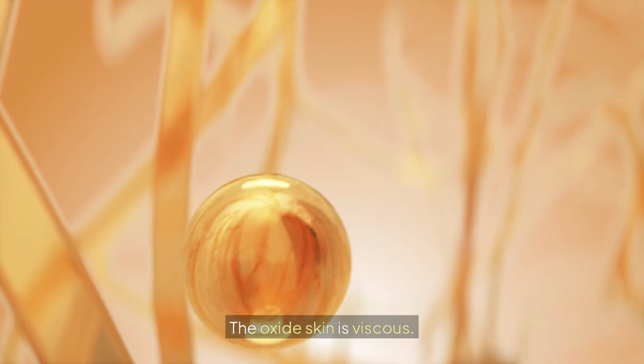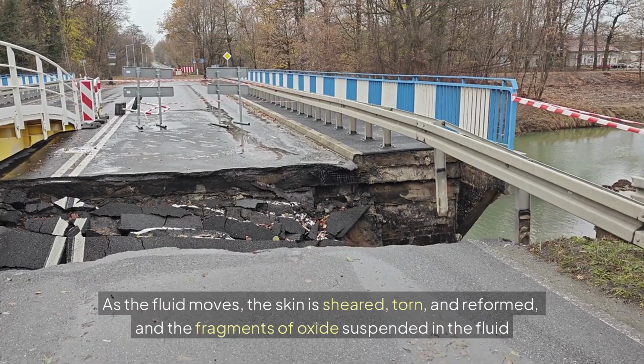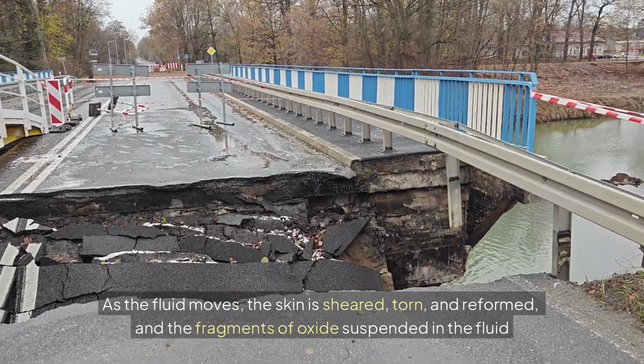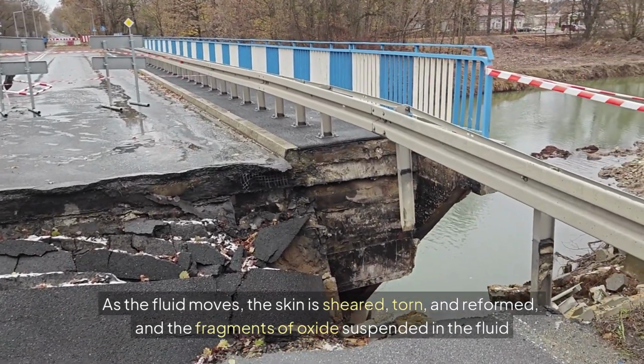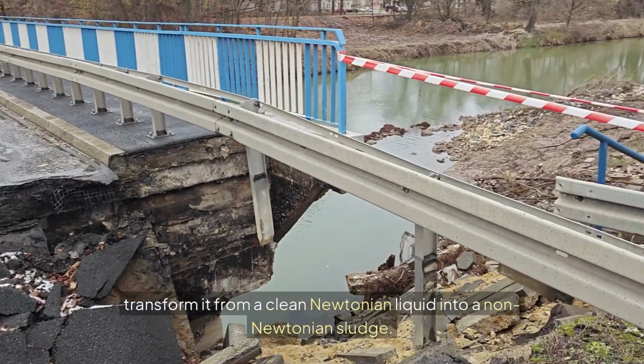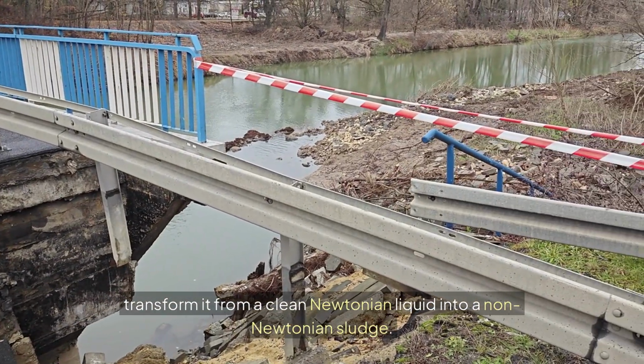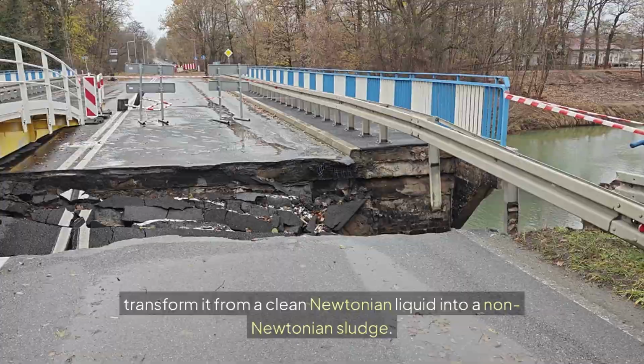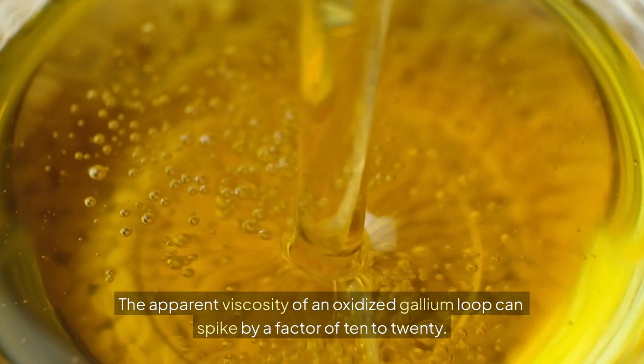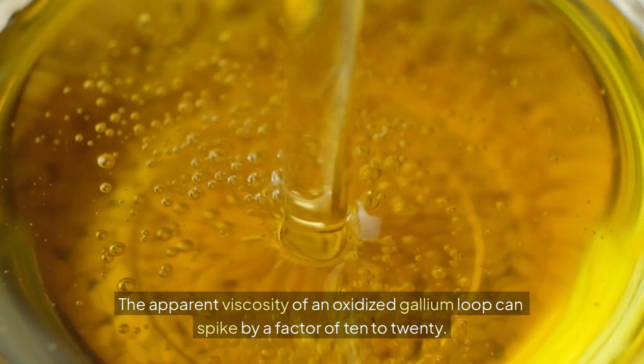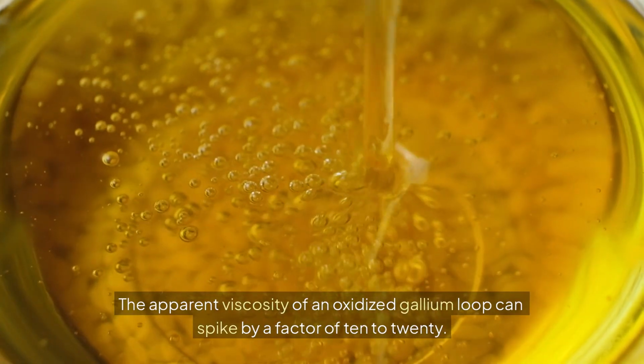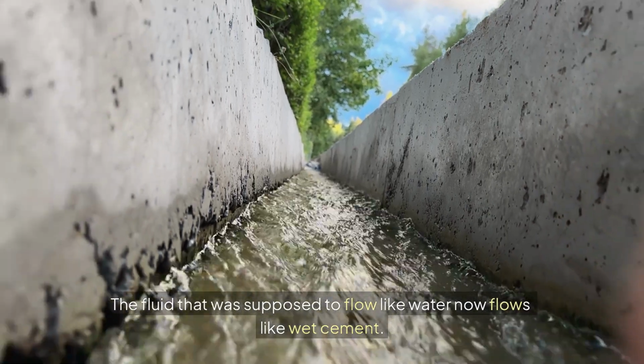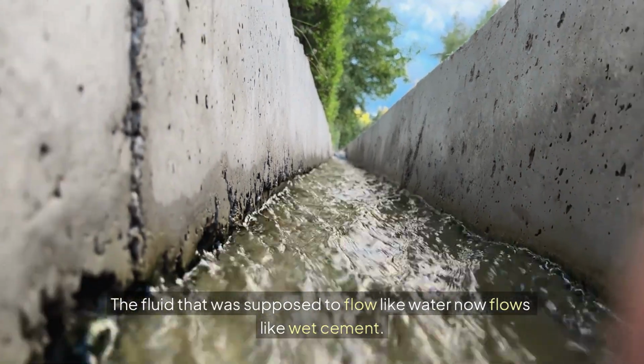The oxide skin is viscous. As the fluid moves, the skin is sheared, torn, and reformed, and the fragments of oxide suspended in the fluid transform it from a clean Newtonian liquid into a non-Newtonian sludge. The apparent viscosity of an oxidized gallium loop can spike by a factor of 10 to 20. The fluid that was supposed to flow like water now flows like wet cement.